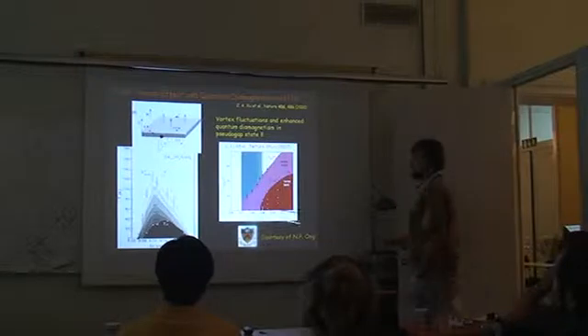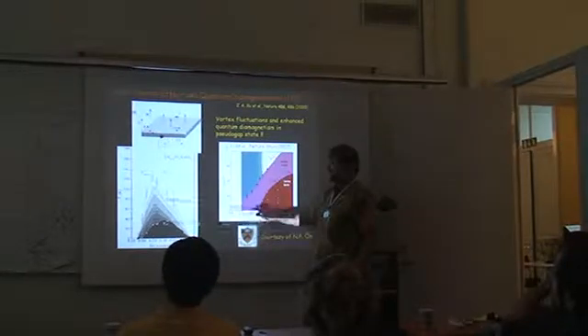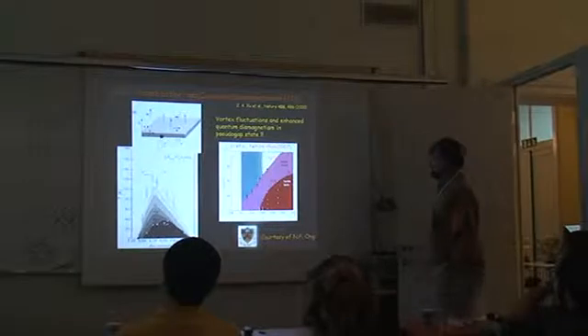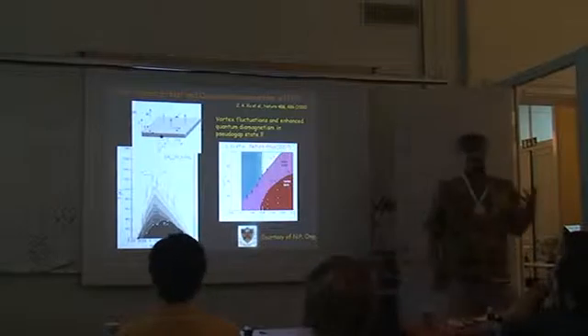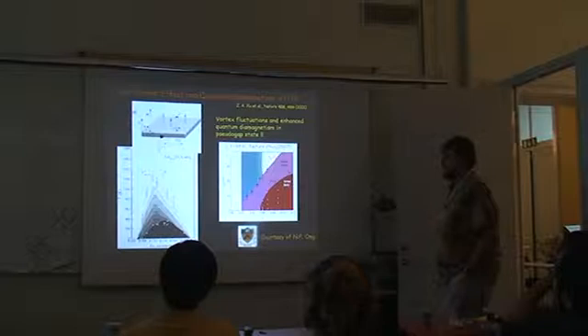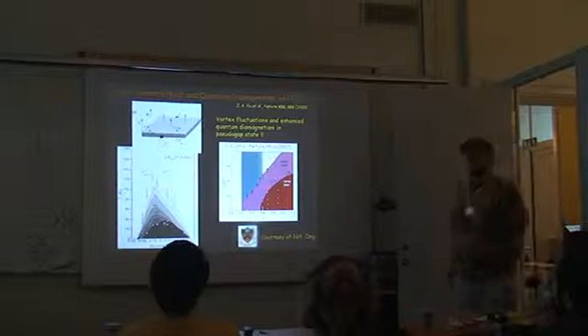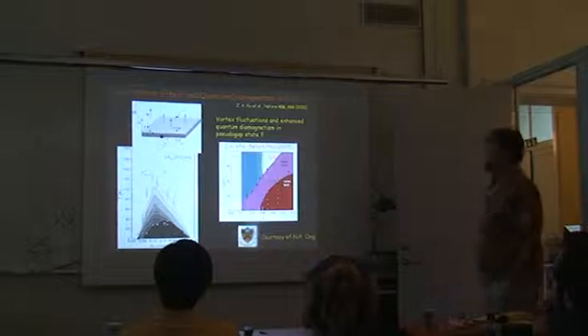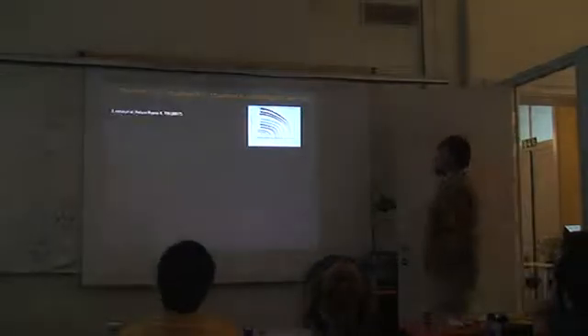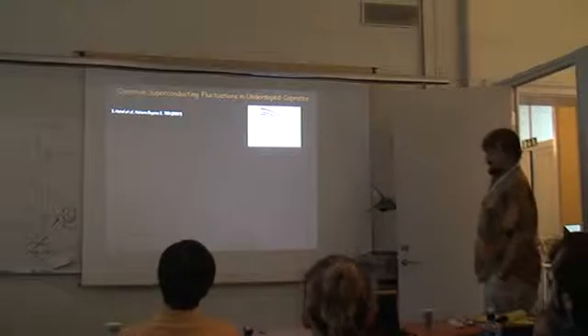These are famous Ong et al. experiments from Princeton, which first of all show very large Nernst effect well above TC in this pseudo-gap regime, and large Nernst effect is an indication of very strong superconducting fluctuations. In fact, Professor Raghu worked on that. You can ask him, he's an expert. They also see a quantum diamagnetism of the size that is typically a signature of superconductivity alone. Once diamagnetism goes above a certain size, you can pretty much be sure that what you have there is an incipient superconductor, because most materials in natural units have extremely small diamagnetism.